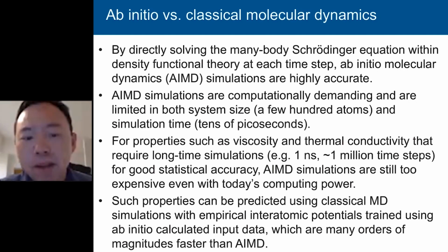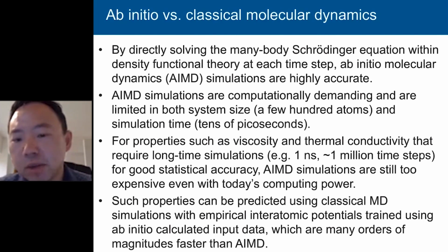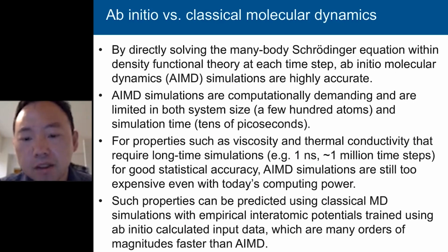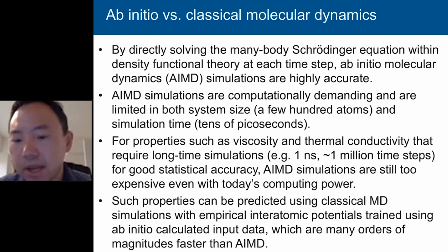So I'm going to show one example to demonstrate this point. So right now, unfortunately, our computing power is still not fast enough to allow Ab-Initio MD to tackle this kind of problem. But maybe in the future, when we have leaps in computing power, we may be able to tackle this problem with Ab-Initio MD. So for now, we use a compromise. Essentially, we rely on classical MD simulations with empirical potentials, which are trained using the Ab-Initio calculated data to predict the thermal conductivity and viscosity data. This kind of classical MD calculation is many orders of magnitude faster than Ab-Initio MD. Therefore, they can get the job done in a reasonable time.